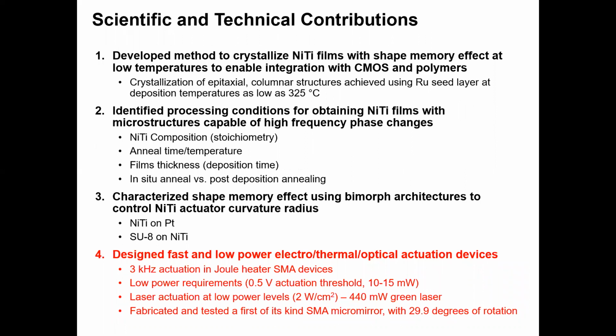So this fourth and final contribution for this dissertation specifically enabled fast and pulsed electrical actuation, in addition to the passive laser actuation of the SMA-MEMS devices. Electrical actuation through Joule heating, coupled with nanoscale SMA films exhibiting good transformation properties and excellent heat sinking configuration, enabled fast actuation speeds up to 3,000 hertz, which is faster than other historical works. Actuation thresholds were shown to be very low, requiring as little as half a volt to initiate this reversible phase change. And finally, a first of its kind SMA micromirror was designed, fabricated, and shown to operate over 29.9 degrees using a nested microactuator design comprised of the SMA film actuator.